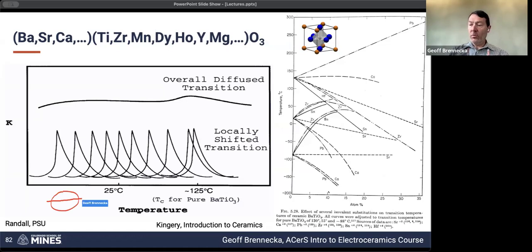So that at one temperature, this region is undergoing this maximum permittivity. And then at a different temperature, the maximum permittivity is right there. So the phase transition is right there. And then we just come up with a gradient all the way across the sample so that some portion of it is always contributing this maximum amount. And then you average it out over the entire temperature range that you care about, and you can end up with a reasonably stable transition.